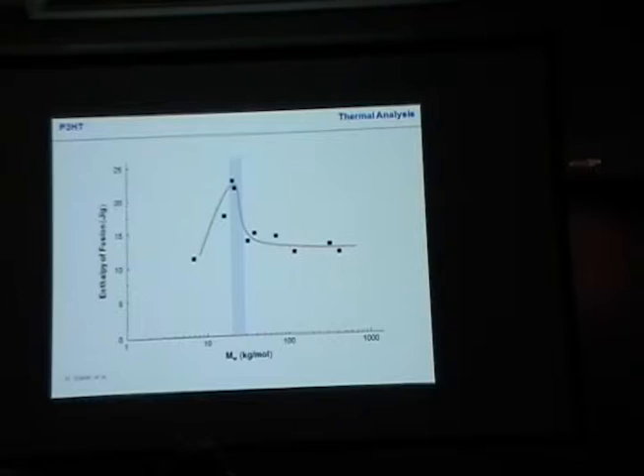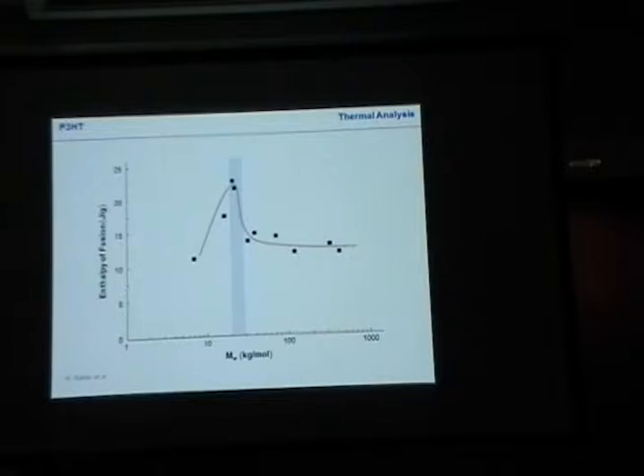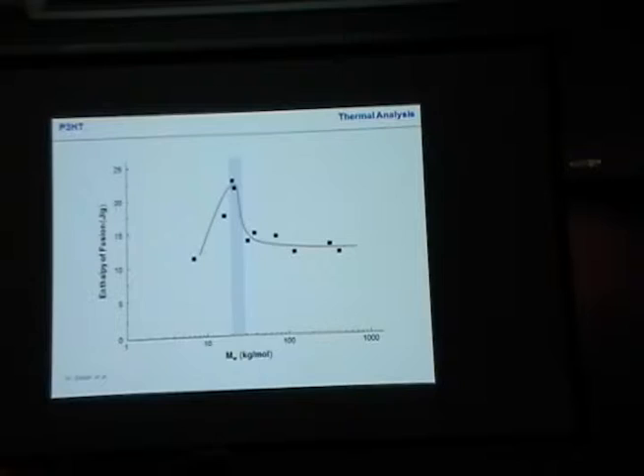The enthalpy gives you how much energy you have to put into a material to melt it. The more crystalline the material is, the more energy you have to put in. You see the trend for different molecular weights. At very low molecular weights, you see the effect of end groups — they really dominate, so the material doesn't pack very well. So the enthalpy of fusion is low, meaning this material has low crystalline order. Similarly for the polymers: they have so many entanglements that they also have difficulties ordering.